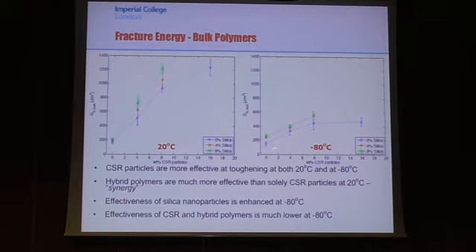We're getting quite a substantial twofold increase here. But we don't see any of this synergistic effect where these lines are diverging. These lines are pretty much parallel. Okay, so adding the silica at either 4% or 8% does have some toughening effect, but adding more of it doesn't seem to increase the toughening effect, and adding it as a hybrid also doesn't seem to increase the toughening effect at minus 80.